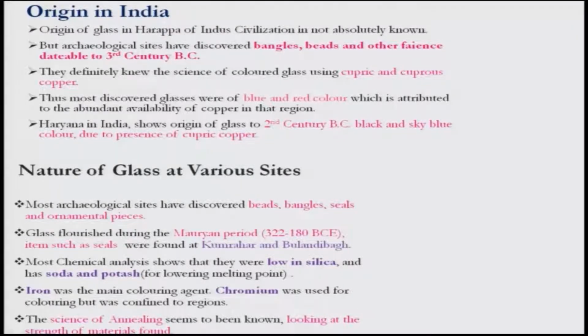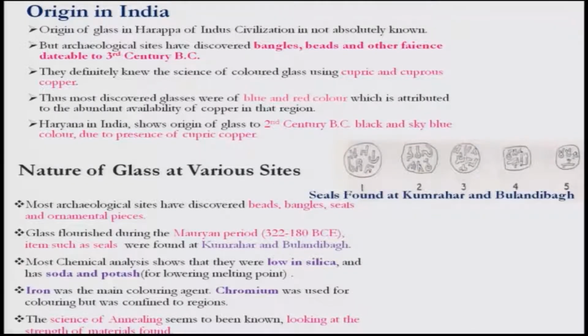Glass flourished during the Mauryan period, because people have found several seals from the Kumrahar and Bulandi Bagh areas. These are the seals obtained from these two sites, and Brahmi lipis are mentioned on them. They were using them as seals. Most chemical analyses show that they are low in silica and have soda and potash, maybe for lowering the melting point of the glass. Iron was used as a coloring agent, because iron was available in the eastern part of the country and some other parts as well. Chromium was also used for coloring, but was confined to certain regions.